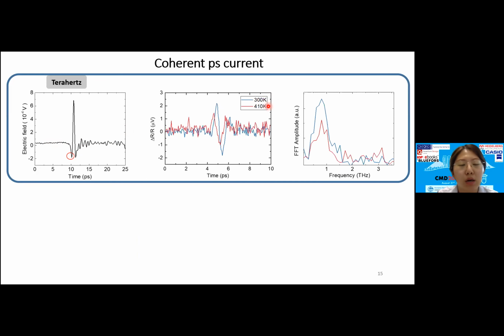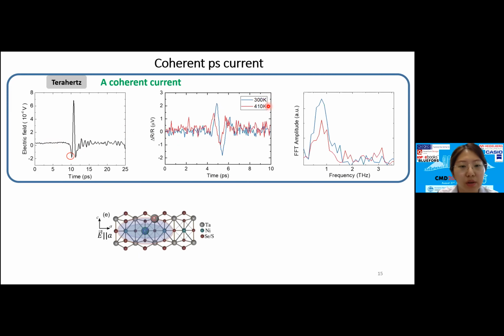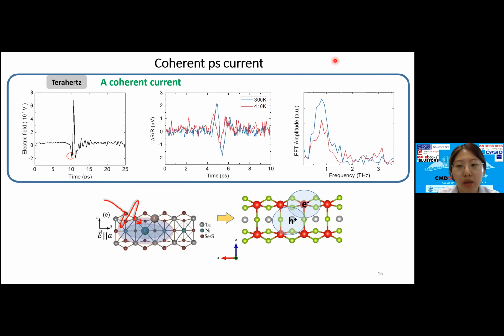So we checked there is a coherent current. The possible interpretation is that if there are intrinsic polaronic complexes in the system, when you pump the system, the excitons can be temporarily broken and they flow, but they flow slowly because of the lattice contribution. So we can generate a driven polaronic current.